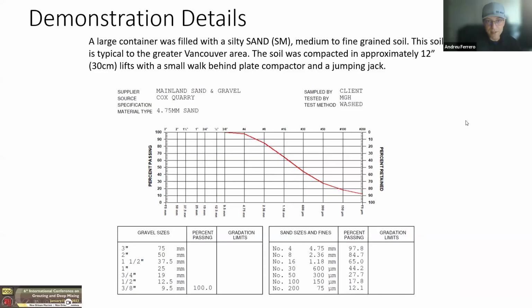So this is a gradation curve for the sand that was used. This was from a quarry in the Vancouver area that is used for construction. As you can see, the silty sand had about a 12.1% fines content. So it was right there in the mid-range of what we would expect to be groutable. Generally, things above 20% fines content are not going to be very groutable. So this was a good example of a slightly dirtier soil that we wanted to use to see what the results would be.